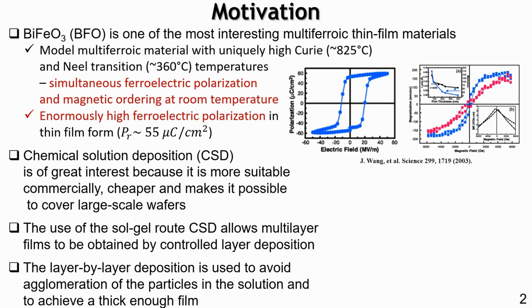Usually, in order to create thick films by sol-gel, people use a multilayer technology, so they deposit layer by layer to achieve the necessary film thickness. For example, if you need a film of micrometer thickness, you need to create 10 or even more layers. The layer by layer deposition is used to avoid agglomeration of particles in solution and achieve a film of higher quality.